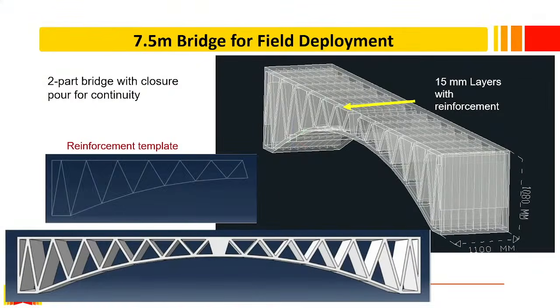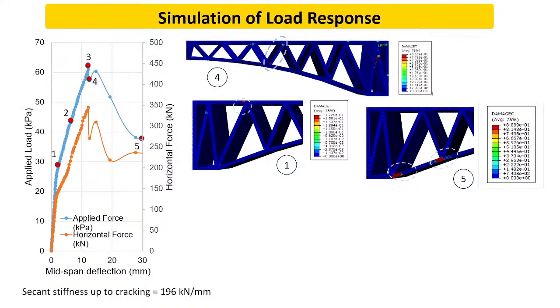And we already have the tensile response, the cohesive response that we got from the fracture test. So I do get some residual tension resistance from this steel template. Now, next was to simulate the response. Here we are getting into predicting it using nonlinear finite elements, using concrete damage plasticity. A proper model was built, and the idea was to be able to predict the load capacity. How much can this bridge possibly take?